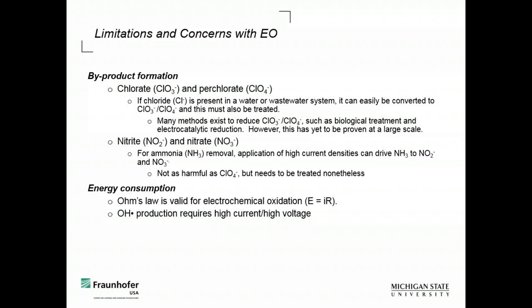Other materials like mixed metal oxides, and specifically Magnéli phase titanium oxide, are probably the biggest competitor to boron-doped diamond. You do not generate perchlorate with Ti4O7. However, Ti4O7 has some issues treating shorter chain compounds. So every single one of these technologies has its own little Achilles heel. So this is going to be a big puzzle. And I already talked about the energy consumption. And then, like I said, for ammonia, we do convert it to nitrate, which could be a problem for a wastewater treatment plant.